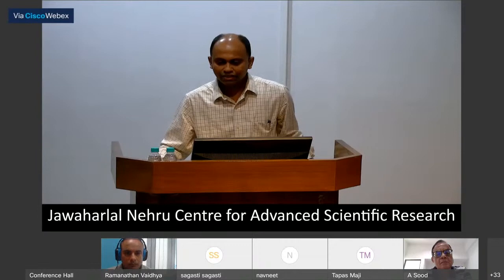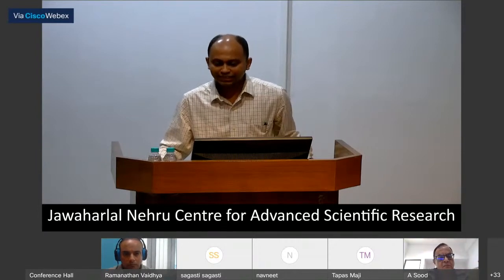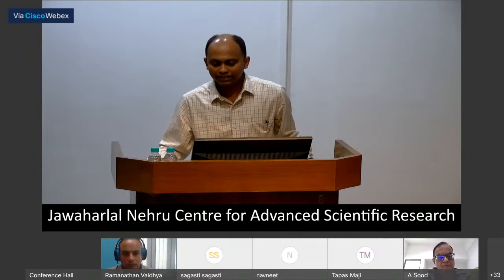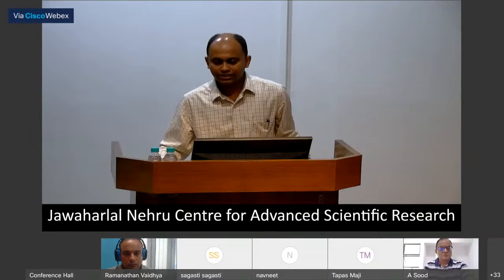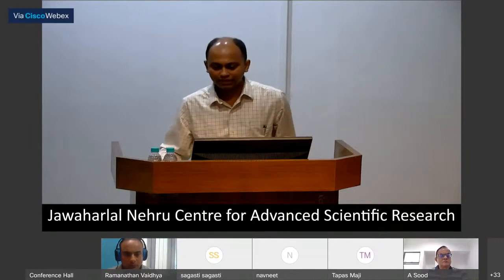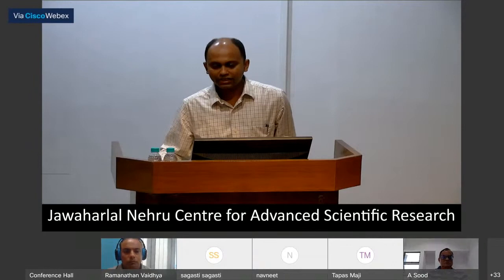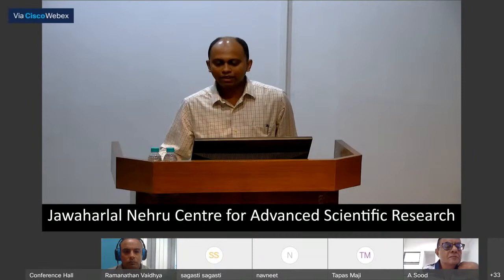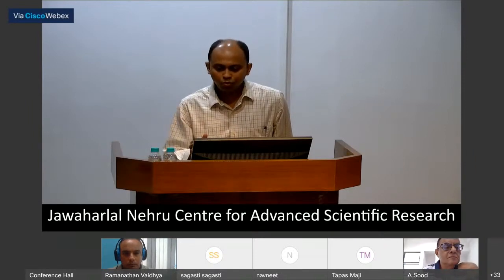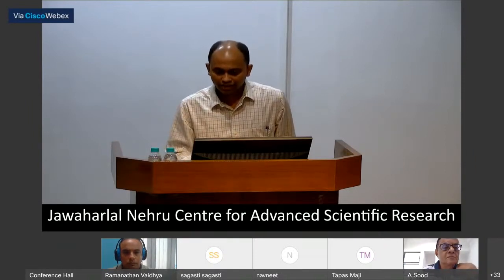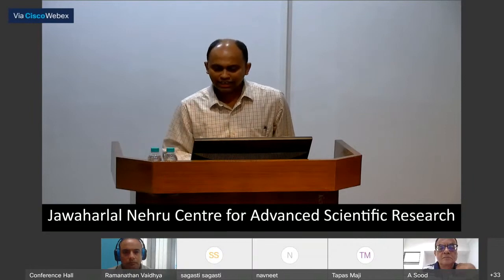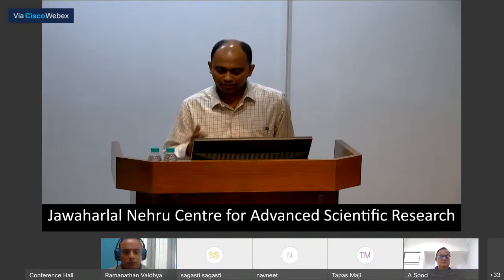Because with twinning, you should see the domains also by HRTEM imaging. That we don't see. You can see the different polarity domains in imaging; this is well known in electron diffraction and TEM imaging. But in this structure, these exact cell-doubling spots are happening without twinning, so that means there is cation ordering. And we have not only this proof; we have electronic transport proof, theory calculation proof, and other experimental proof as well. So we are not claiming based on a single experiment.